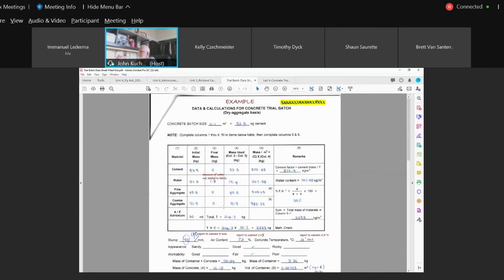In this example, this group did not need all their mixing water. They eyeballed the slump in the mixer. Typically you can drop some concrete out of your mixer and do a slump test, but again, you're taken away from the mixing time criteria. Keep in mind that trial batches also have to follow a CSA sequence. It's a test like any other test.